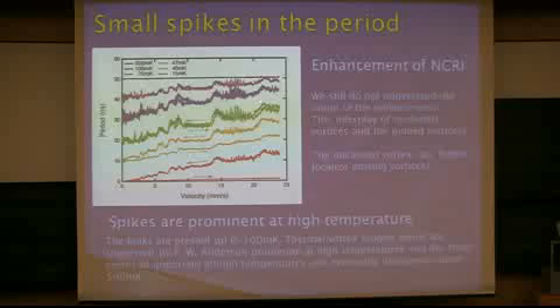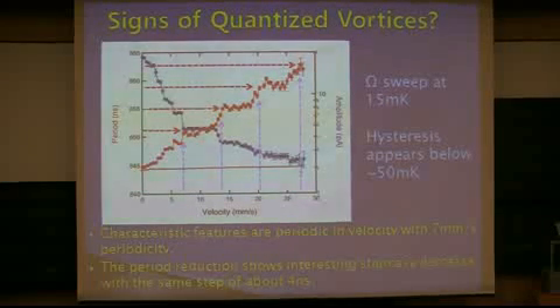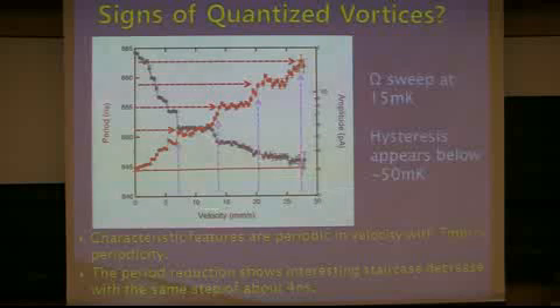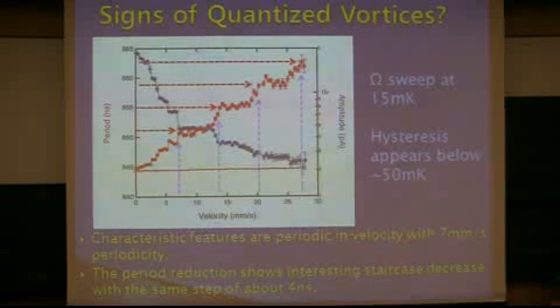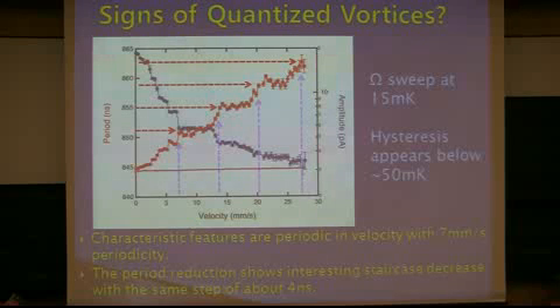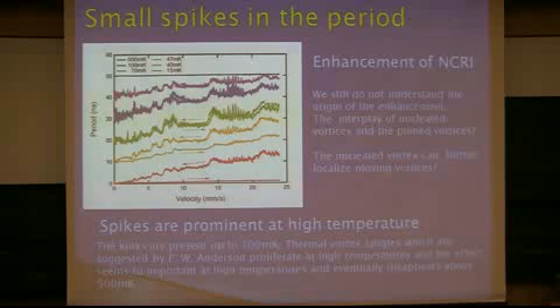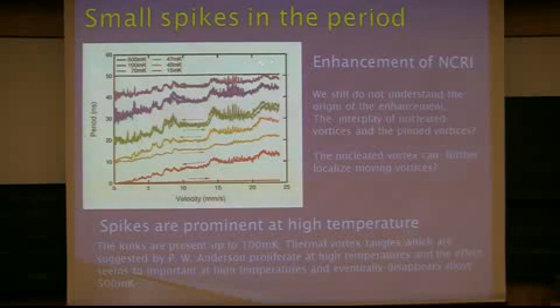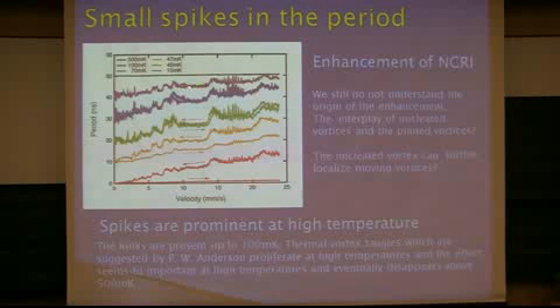First of all, what we found, sorry, I forgot to explain. When you increase the DC rotation back, there is no change in the resonant period. Once you go back to the minimum state, even if you increase the DC rotation, you cannot destroy it. And that's the hysteresis. This kind of hysteresis is prominent below about 50 millikelvin. It's greater and greater when you decrease the temperature. And staircase-like structures persist all the way up to about 100 millikelvin. Above the onset of transition, there are no staircase-like structures. These structures only appear with the existence of non-classical rotational inertia.